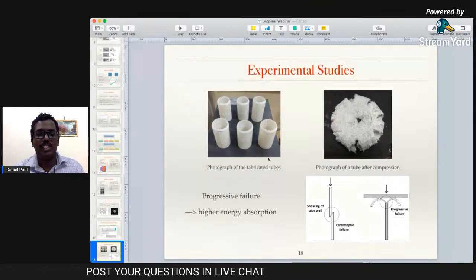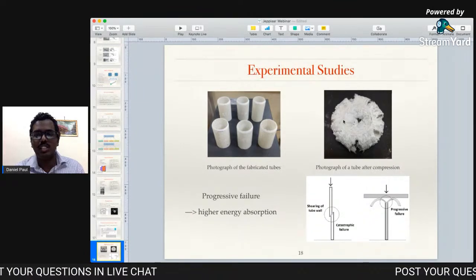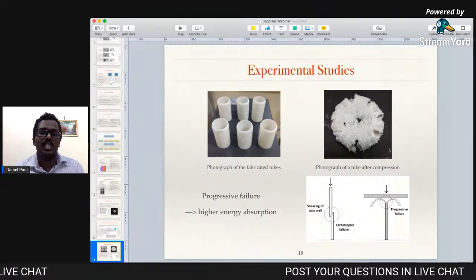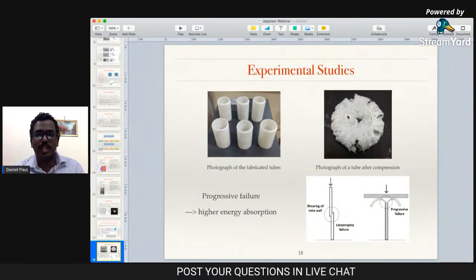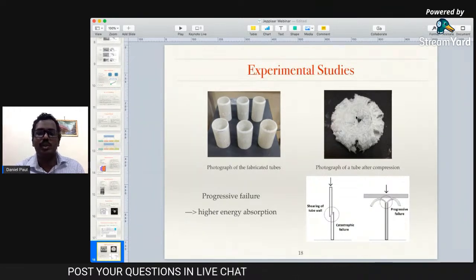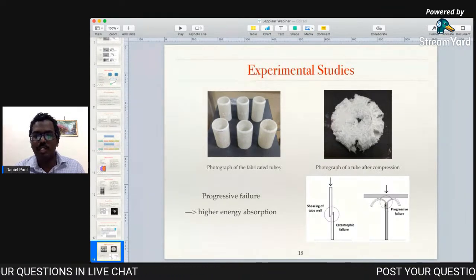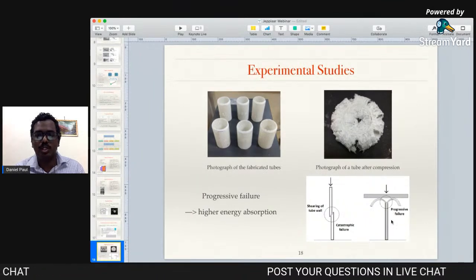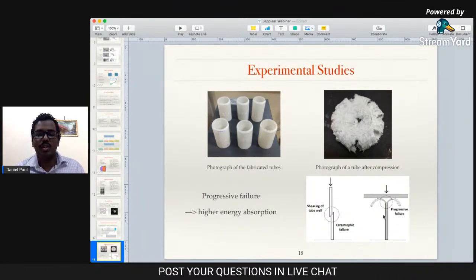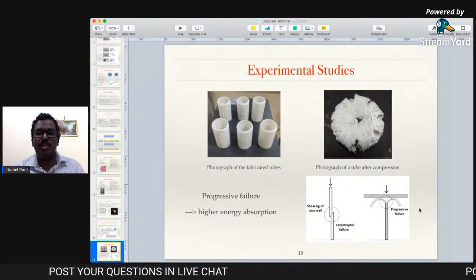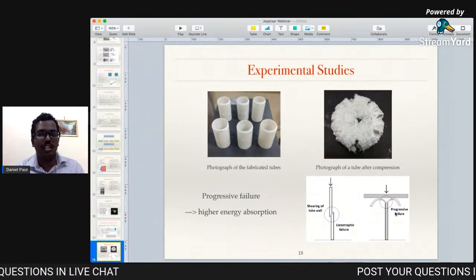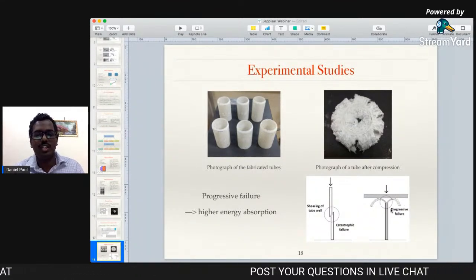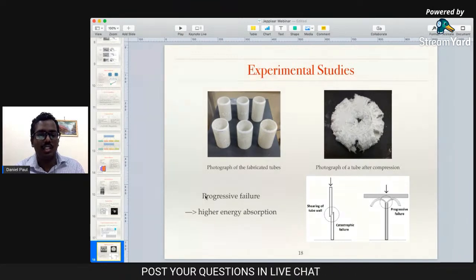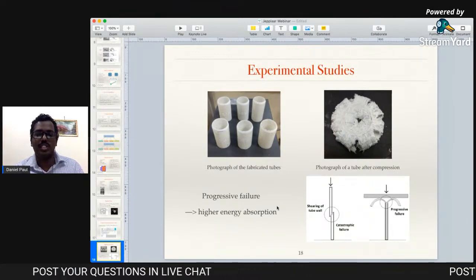It's just going to break off at an instant. But when we compress these tubes, it gives rise to this petal kind of formation. So these walls are split and they bend inwards and outwards, and they give a kind of petal formation, which aids in progressive failure. So when you deform something progressively, you're doing it for a long time. You're elongating the time of the compression, and this leads to higher energy absorption.